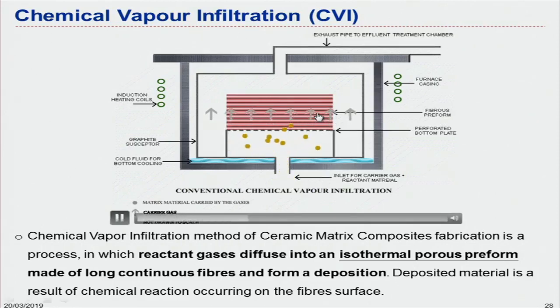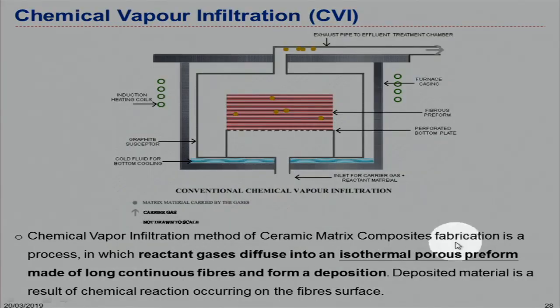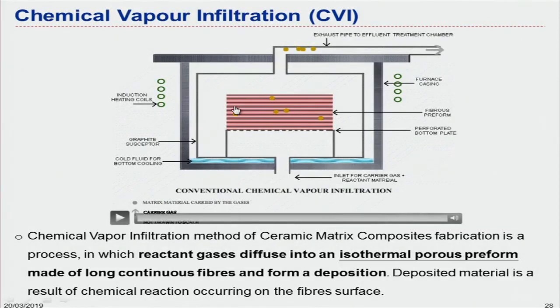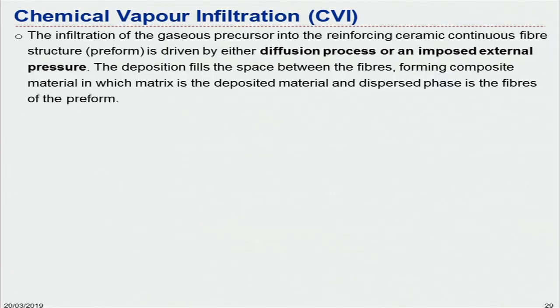Looking at a simple simulation of the process, a few things are really important. You can see the isothermal preform — we have to maintain the temperature of the chamber uniformly. If the temperature is different in different areas, the decomposition rate and the thickness of matrix material deposited onto the fiber surface will vary. We want homogeneous decomposition of the matrix material, so we must maintain the same temperature throughout — there is a chemical reaction occurring under isothermal conditions.